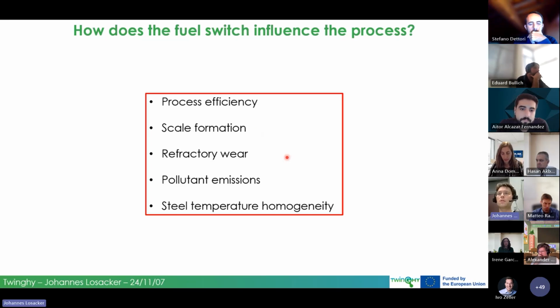Then another material that's in contact with the furnace atmosphere is the refractory. So that's like the lining at the inner furnace wall that's protecting the walls from the heat. So we expect some interdependency with the flue gas atmosphere there as well. Then we have one important point, which is pollutant emissions. Mainly we focus on NOx emissions because the higher flame temperatures of hydrogen flames make it a bit uncertain how these emissions will evolve. They will get higher, lower, whatever, this is to be investigated within the project.